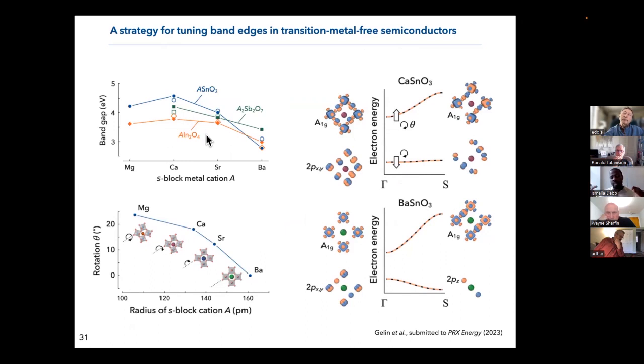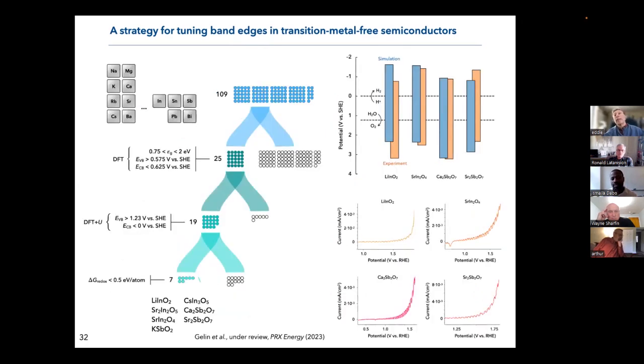So to make a long story short, essentially, when you insert S block cation into the mix, they not only enable you to be less electronegative, so they bring up the energies, making you more aligned with the redox potential of water, but also because of the distortion that you have in the structure, you can adjust the band gap. So it's really a win-win situation for us, where we can not only adjust the band edges, but we can do so without necessarily increasing the band gap due to the insertion of those very electropositive elements that make the material more electropositive.